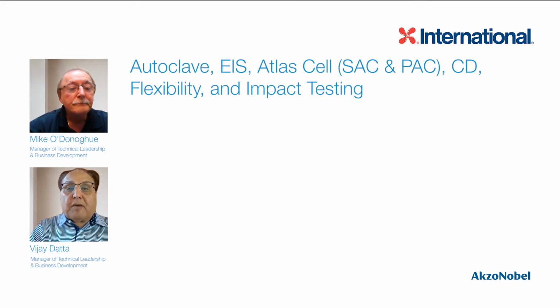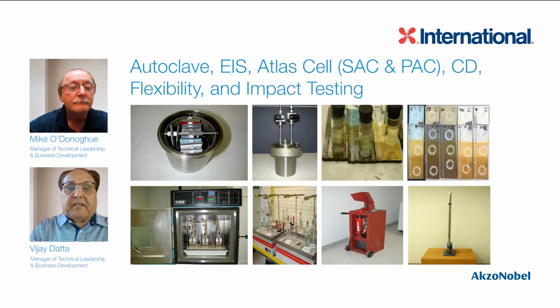As you can see here on the top, we have an autoclave set up here. It's like a pressure cooker, which can have 3 phases: gas, hydrocarbon, as well as water. And what we will do is we run this test for several months under different temperature conditions, and then we measure the EIS values, which is electrochemical impedance spectroscopy, that gives you the barrier properties. And then at the bottom, we have Atlas cell set up there, cathodic disbondment, impact, and flexibility test.